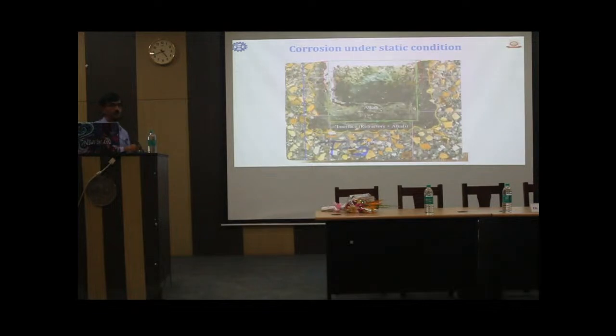But in the case of a brick or some standard refractory, it is not a very dense material. Some 12 to 14% porosity is there, unless it is a fusion cast refractory, so there may be some sort of penetration. You see, I just marked it with the yellow color. If you put some alkali and heat it for some time at a particular temperature, this is the infiltration. Since there are aggregates and grains of different sizes, the infiltration depth may not be fixed, it will vary. You have to take the infiltrated area instead of the infiltration length. We can calculate the infiltrated area, and this is actually the wear out of the material by means of chemical reaction.